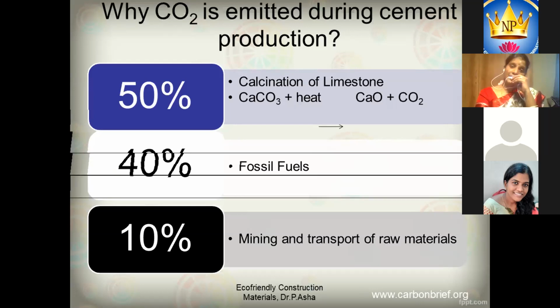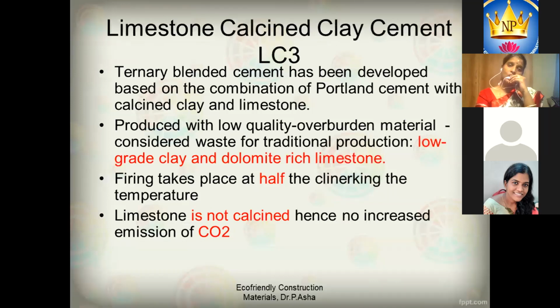And next one is the limestone calcined clay cement. It is a hot topic and is being researched by many people. This is nothing but using low grade clay and dolomite rich limestone. The firing will take place only at half the temperature. Generally in cement production, you are heating the limestone to about 1450 degrees centigrade, a very high temperature, which emits the carbon dioxide gas. Whereas in this type of cement, the temperature is only half, that is around 700 to 800 degrees centigrade. So the emission of carbon dioxide will also come drastically down.